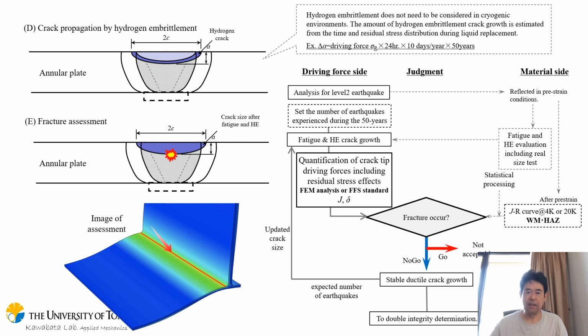And then we must consider hydrogen embrittlement. As explained before, hydrogen embrittlement never occurs at 20 K with a full storage tank of liquid hydrogen. In other words, consider the case when the liquid is depleted and the temperature inside the tank rises to high temperature. The fracture driving force is the internal stress, which is mostly welding residual stress.